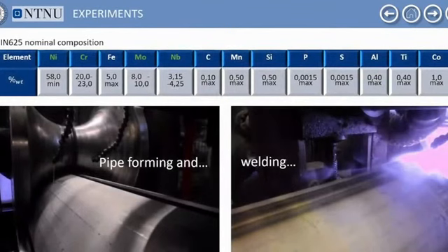This table collects the nominal composition of the alloy. I have highlighted in green the most important element, the key element for corrosion properties. In particular, nickel and chromium are used against oxidizing environments at high temperature, while molybdenum and niobium are used against local corrosion.